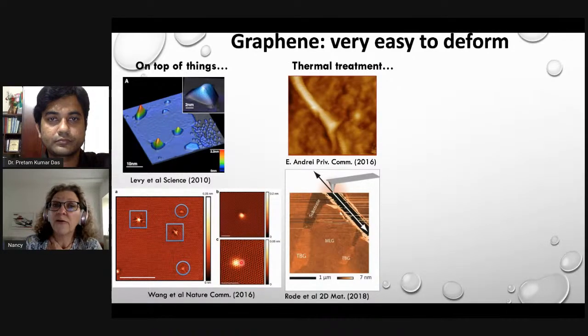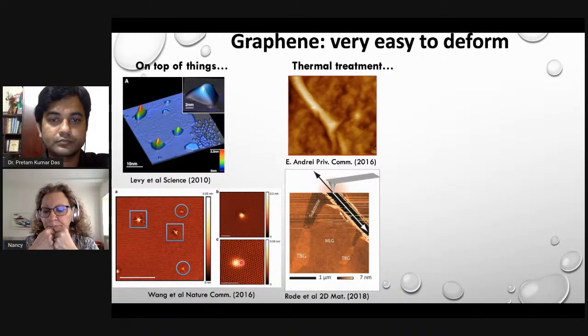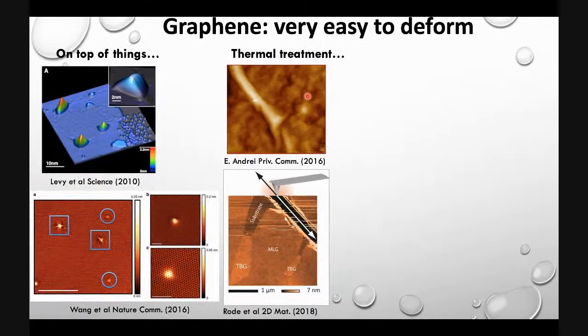Graphene was also easily deformed when it was under thermal treatment, when deposited on the substrate and annealed. Because of the different thermal coefficients of the substrate and the graphene membrane, the material deformed differently, and after the thermal treatment, it was observed the appearance of folds or wrinkles. Like when you put a tablecloth on the table and you stretch it and you compress it and you have folds forming on the tablecloth. Well, something like that happened here after thermal treatment.